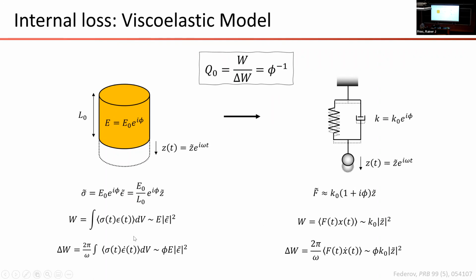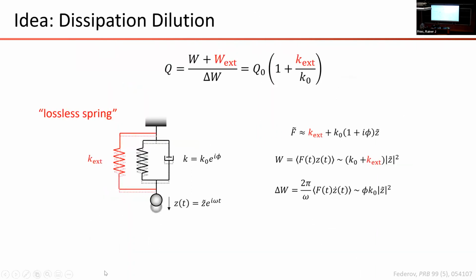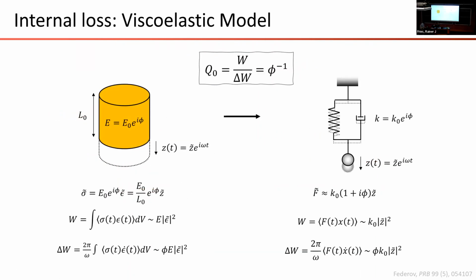So that out-of-phase component of the strain basically introduces a force; a component of the stress is out of phase with the strain. So it's like displacing a mass from a spring, and that gives rise to a restoring force that's proportional to the velocity. What that means is that there is power dissipated, and this power dissipated is proportional to the cycle-averaged stored energy, and the proportionality is given by this phase shift, this complex argument of the elastic modulus.